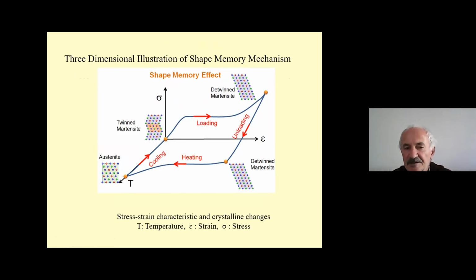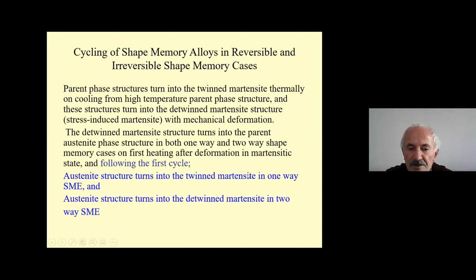This is the three-dimensional illustration of the shape memory mechanism. On cooling, the ordered parent phase structure turns into twinned martensitic structures by means of thermal induced martensitic transformation. With the deformation, twinned martensitic structures turn into detwinned martensitic structures by means of stress-induced martensitic transformation. On heating, the detwinned martensitic structures turn into the ordered parent phase structures by means of reverse austenitic transformation, and the crystal structure of the material cycles between ordered parent phase structures and twinned martensitic structures on heating and cooling.